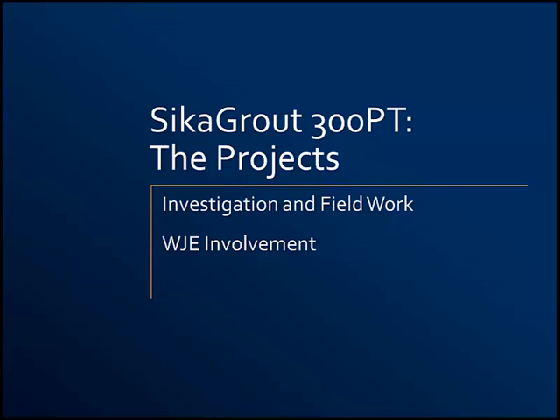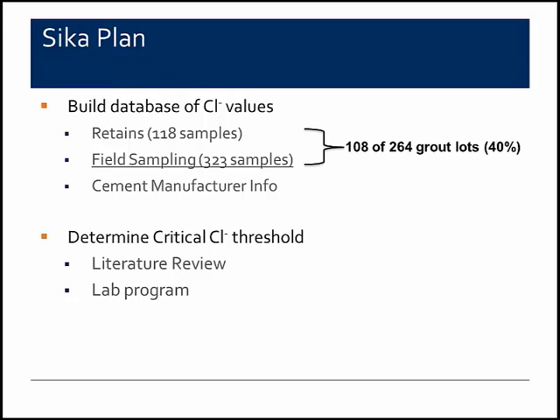And the plan that Sika developed to try and assess the significance of the chloride issue was two-pronged. And the first prong was to build a database of all of the chloride content values that had been generated by the Marion, Ohio facility between 2002 and 2008. And that was done through testing of retains, and where there was not retained data available, through field sampling, collecting grout samples on existing bridges and testing them for chloride content.